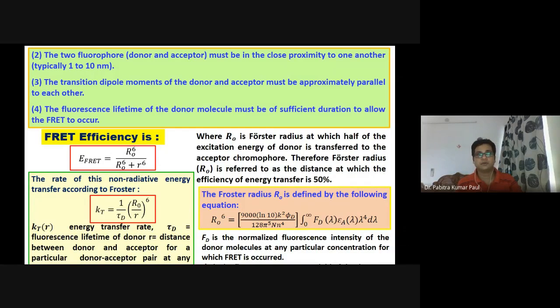1 by tau d, R0 to the power 6 divided by r to the power 6. And what is the small r? Small r is the instantaneous distance between the donor and acceptor molecules, at any time. And kT is the energy transfer rate, and tau d is the fluorescence lifetime of the donor, and r is the distance between the donor and acceptor, as I told you already, for a particular donor acceptor pair at any given conditions. And this Förster radius is also defined by the following relation, and there are theories available in the literature. You can also go through the theory of FRET to have some idea about this theory.